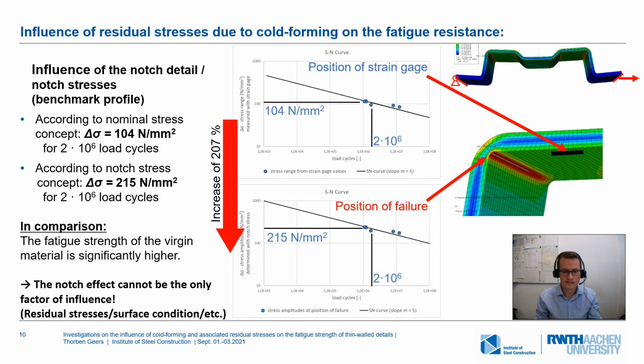If the increased stress in the notch base is now taken as a basis, this results in an increase of over 207%. The fatigue strength is then 215 Newton per square millimeter. But bear in mind that the fatigue strength of the virgin and the pre-stretched specimens is significantly higher in the yield strength range. This at least shows that there are other factors which influence the fatigue strength, for example, residual stresses or surface conditions.